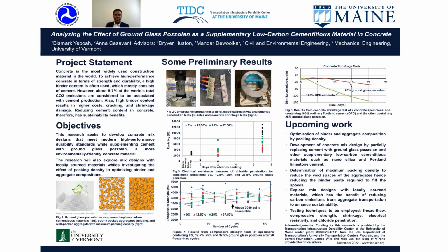So in figure 1 on the left, it shows ground glass pozzolan as a supplementary low-carbon cementitious material, as we have here. And this material comes from recycled waste glass, ground to the fineness of cement. The figure in the middle shows poorly packed aggregates, which require a relatively higher volume of binder paste to fill all these pore spaces, as compared to the figure on the right, which has maximum packing density and will require relatively lower binder paste to fill the void spaces.